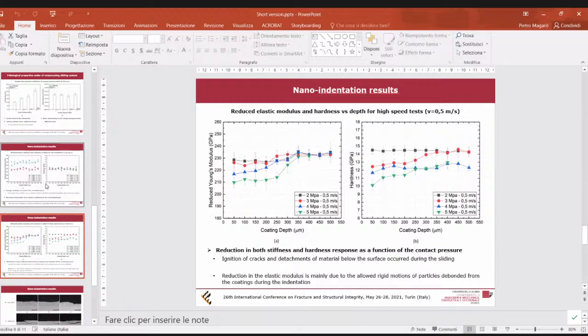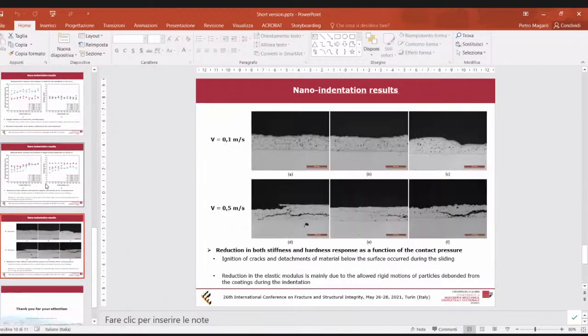The main conclusion is that the damage mechanisms are different, depending in particular on the sliding speed. And these latter results can be related also to the evolution of the microstructure, to the modification of the microstructure of the coatings along the thickness. In fact, in the case of 0.5 meter per second, very large cracks can be observed in the thickness. In the case of 0.1 meter per second, they are absent.